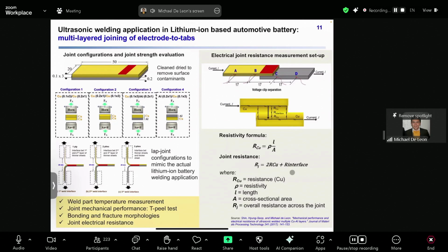For the key contributions, first, the lap joint configuration here is very critical, so we have to look at proper positioning of the thin sheets, which directly influences the weld integrity. There are hidden defect challenges here, like UW achieves sufficient metallurgical strength, but it may leave undetected unbonded interfaces, such as voids and gaps, which actually was created from the non-uniform plastic flow, and subsequently will increase the electrical resistance.